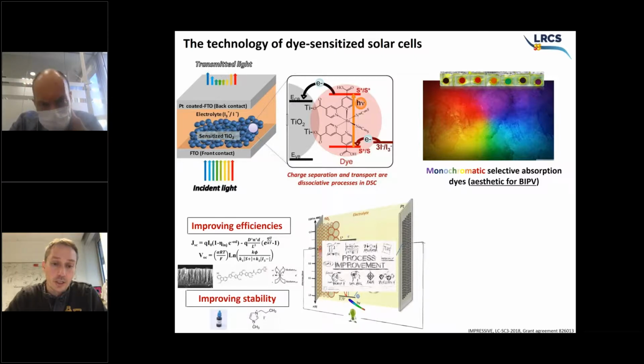Looking at the state of the art in the field of dye solar cells, mainly the research work was devoted to improving the efficiencies. Today, the efficiency of dye solar cells is 14.2%. And typically, to improve the efficiency, one would develop a dye which absorbs as many photons as possible, so panchromatic absorption and a high molar extinction coefficient. And secondly, you need to reduce as much as possible the energy losses, which typically come from a mismatch of energy alignments between the redox mediator and the HOMO level of the dye, or between the conduction band edge of the titania and the LUMO level of the dye.